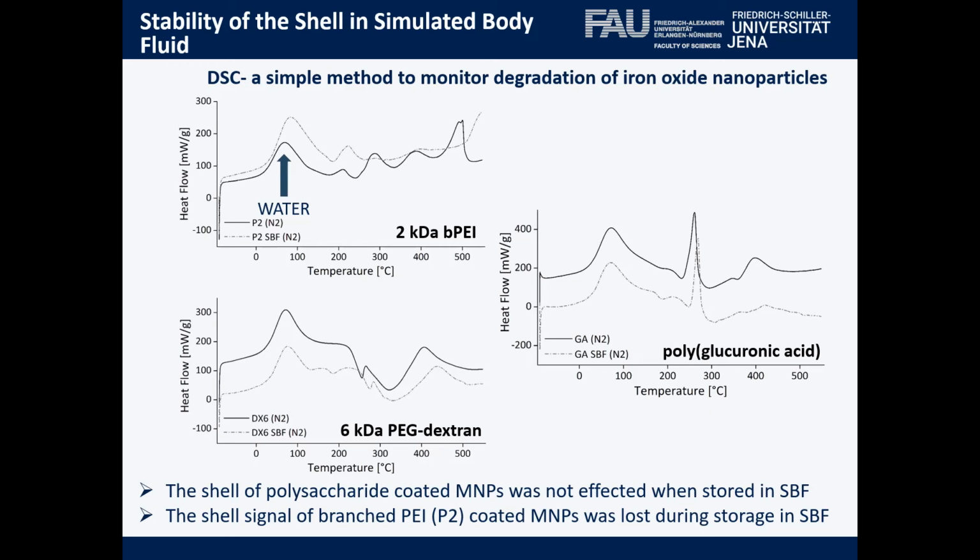And what we found was that the shell of the polysaccharide-coated magnetic nanoparticles, so this means the PEG-dextran and the polyglucuronic acid, was not affected after storage in SBF, because the signal after storage is highly comparable to the signal before storage. And we also found that the shell signal of the branched PEI-coated nanoparticles was lost during storage in SBF.